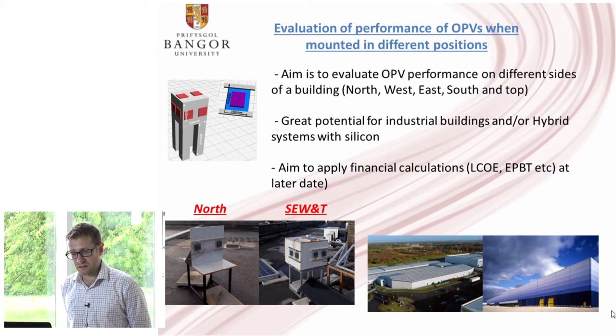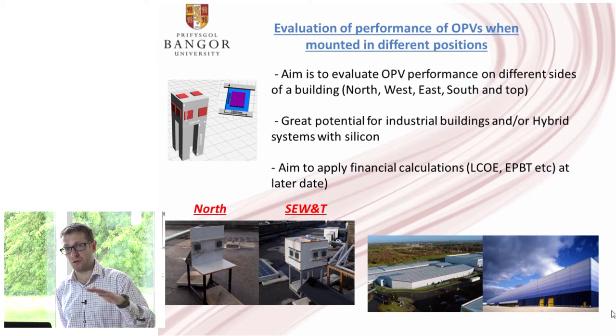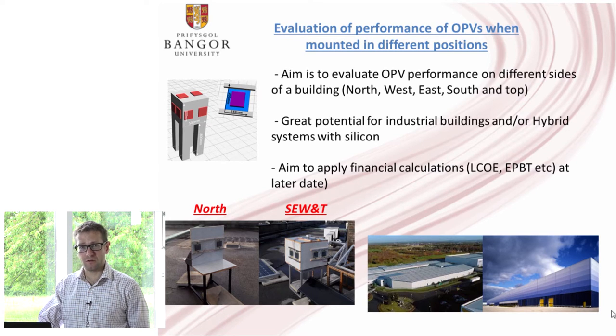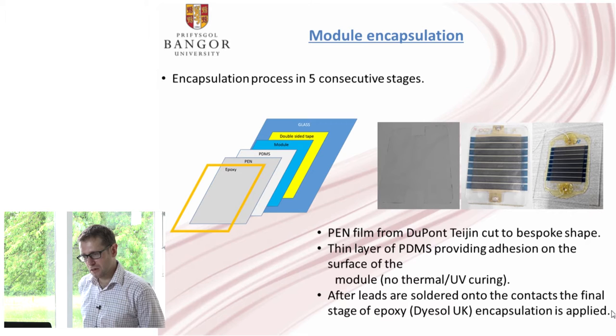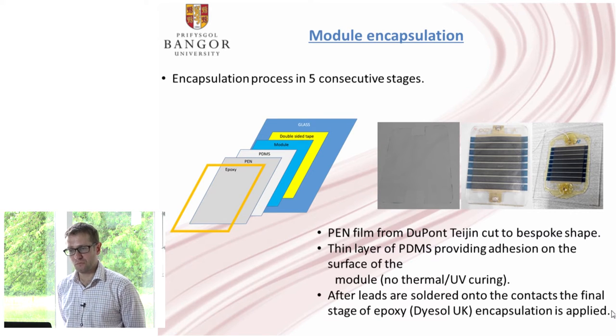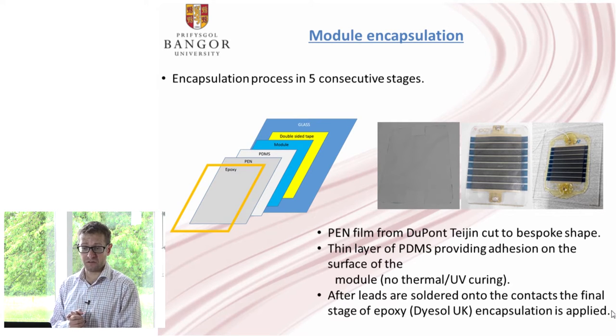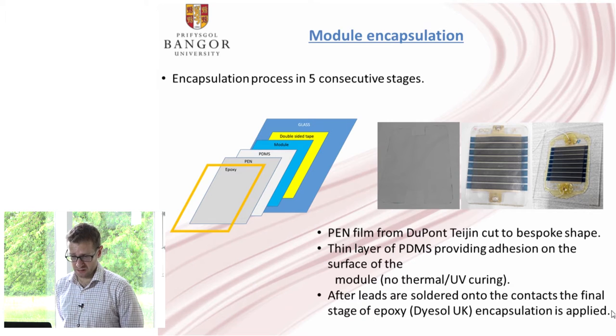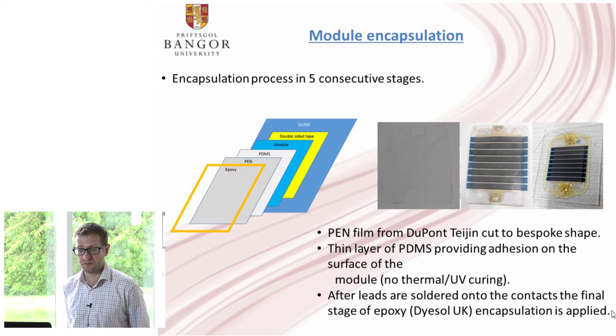So what we've done is develop a setup in Bangor where we can evaluate the performance of organic solar cell modules when they're facing the north, facing the south, facing the east, west, and also modules on the top. And what we're really trying to do is calculate the energy yield from modules directed in these different directions. So in terms of the module encapsulation, what we tend to do is we get modules from Infinity PV in Denmark, and then we apply a PEN barrier layer onto the surface. And one of the important steps we find is to use very good edge sealant. So we get edge sealant from Dyesol, and that allows us to provide a good barrier for our solar cells.